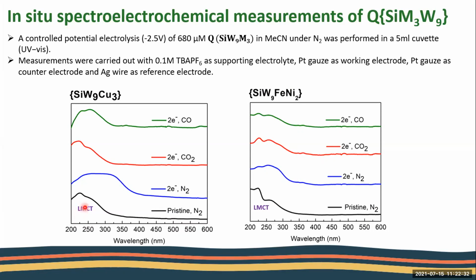And you can see that when we start to reduce that under nitrogen, we have immediately the Jahn-Teller effect. That means that we have a mix of copper. We have copper 1 that reduced from copper 2, and we have also copper 2. And then when we start to add CO2 or CO, we have oxidized back the metal again, and that means that we have some binding between the CO2 or CO with our catalyst. In the iron nickel 2, we have more or less the same phenomena, but it's less strong.